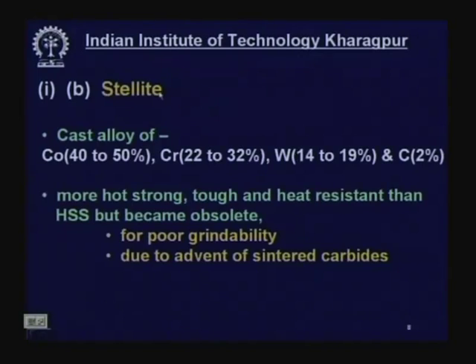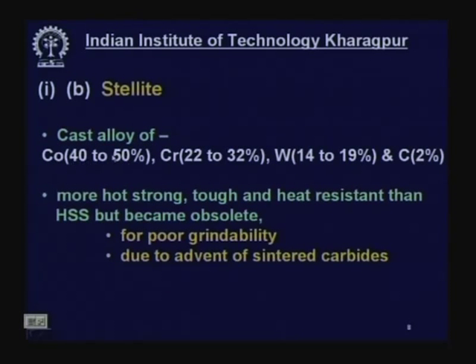Stellite is a novel material developed around 1913–14. It is produced by casting — not by powder metallurgy — and contains no iron. It is composed of cobalt 40–50%, chromium 22 to 32%, tungsten 14–19%, and carbon up to 2%. These materials are melted and cast into tool bits, which are then brazed onto a tool shank and used for cutting.